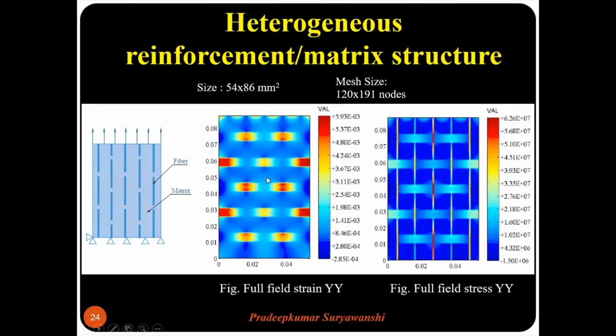This particular diagram shows the full field strain and full field stress. Again, similar to what we observed in central reinforcement, we see near the tip of the reinforcement, so you can see here is the tip of the reinforcement, the maximum strain and large deformations. And there are so many in this case because it is staggered, it is not uniform. All of these places are possible areas where a crack can initiate and start propagating.